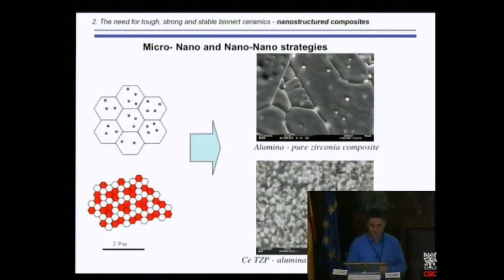We said in the previous presentation that we are now able to process micro-nano and nano composites. This is a schematic example of a micro-nano composite in which we have zirconia particles inside an alumina matrix. This is a nice photo I showed you before. We are also able to make nanocomposites in which both zirconia and alumina are at the nano size. This is a composite which I call micro-nano: the alumina is on the micron size and the particles are nanometric. And in the nano composite, both phases are on the nanometric scale, a few hundreds of nanometers at least. This is alumina with pure zirconia. That's important to say. Also important to say, this is alumina plus ceria-stabilized zirconia ceramic.